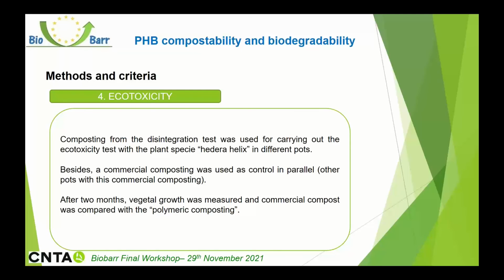Regarding the last essay, after selecting those prototypes which had fulfilled the previously tested criteria, we carried out the ecotoxicity test. For this, we used the plant species Hedera helix, and we measured its growth capacity on 2 kinds of compost: commercial compost, a reference growth criterion, and our compost produced in the previous disintegration test. After 2 months, vegetal growth was measured and commercial compost was compared with the polymeric composting in order to quantify the difference.